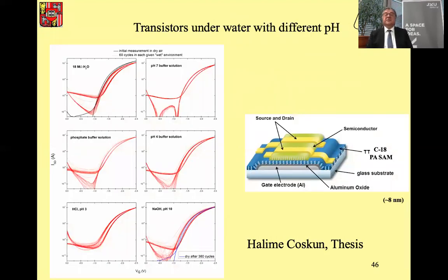The first thing we need is a material, a device which operates underwater. And if you take normally a normal organic semiconductor, put it underwater, it's actually not so stable because photochemically it will degrade if you shine light on it or make electrical currents through it. But this was an eye opener for us. For example, here indeed we have done this organic semiconductor, especially these epindolidiones, are very good stable underwater under different pH. This was the Halime Coşkun thesis. And this is the first criteria. We need, of course, semiconductors and devices which are stable underwater, even without encapsulation.